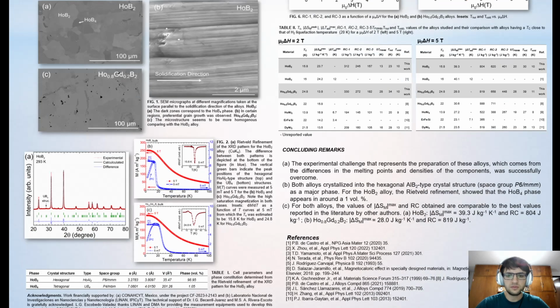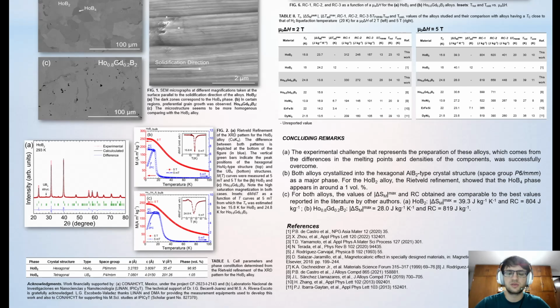And we conclude that the experimental challenge posed by preparing these alloys was successfully overcome. Both alloys crystallized into the hexagonal phase that we mentioned before, and we have a little holmium tetraboride impurity. For both alloys, the values of the magnetic entropy change and refrigeration capacity are comparable to the best reported in the literature by other authors.